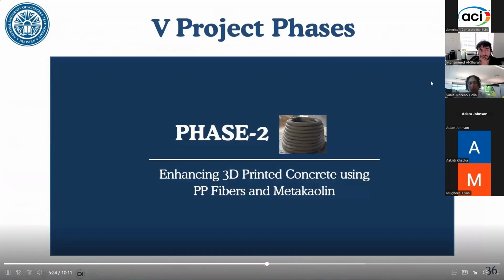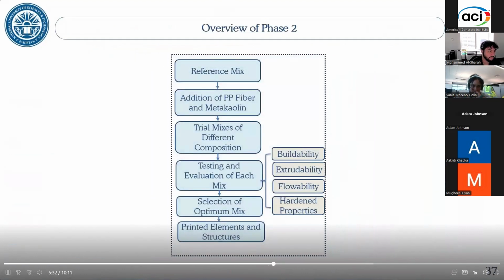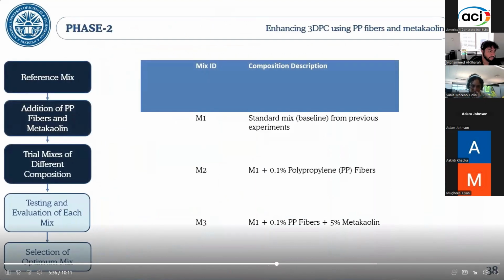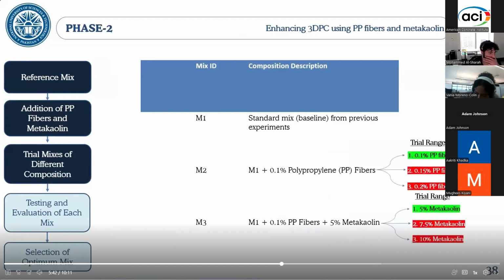Once we established our base mix, we sought to improve certain properties of our base mix with the addition of polypropylene fiber and metakaolin. This is an overview of our methodology for phase 2. To improve crack resistance of our mix, we added the polypropylene fibers. This is the trial range we used. 2 and 3 were rejected because their print quality was too poor.